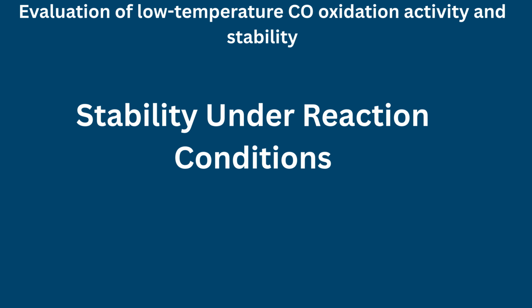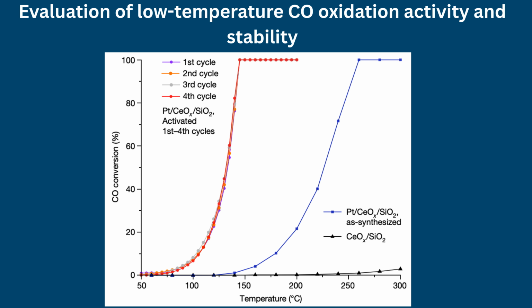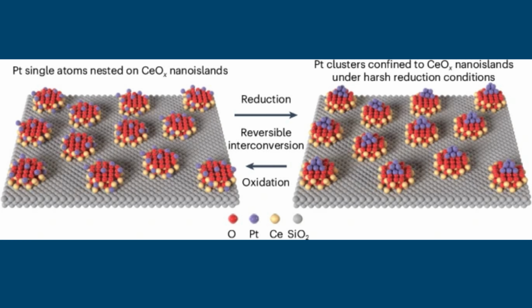Stability under reaction conditions. A defining advantage of the nanoglue strategy is its exceptional stability under harsh catalytic environments. Platinum atoms confined to cerium oxide islands remain atomically dispersed under both oxidizing and reducing atmospheres. No significant sintering occurs even after prolonged exposure to hydrogen at temperatures up to 600 degrees Celsius. In contrast, platinum atoms supported directly on SiO2 or bulk CeO2 readily aggregate under similar conditions.